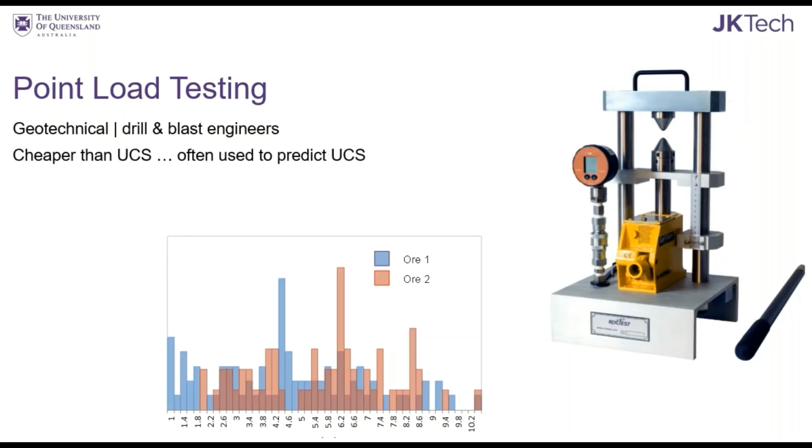And for some clients we've dealt with, the point load test has been related back to an Axb from an SMC test, for instance. So you can basically relate that to throughput at the end of the day. Generally, they show a lot higher error, but obviously that depends on your use case. So for some clients, it's obviously good enough for them.